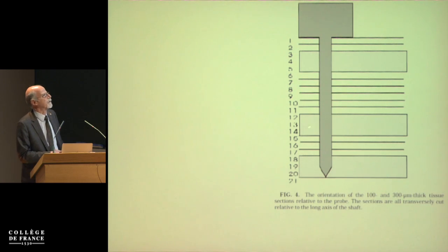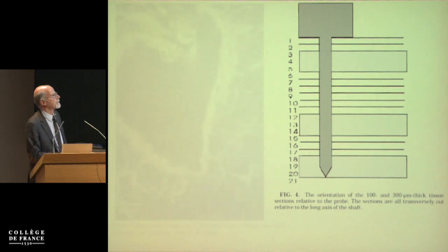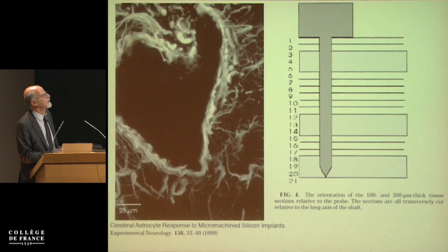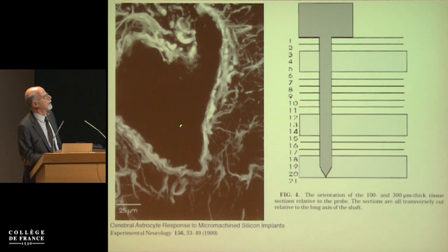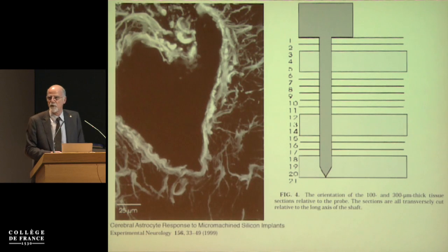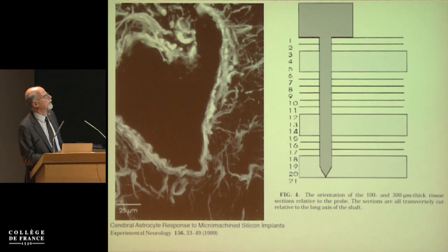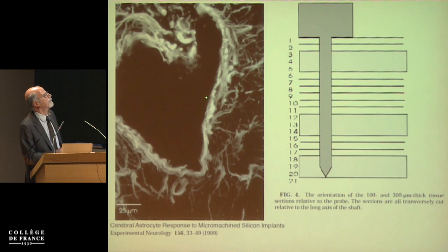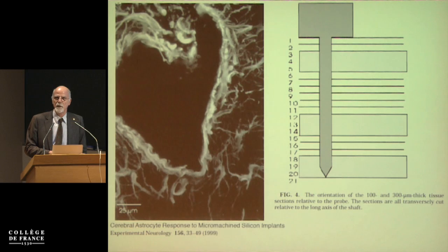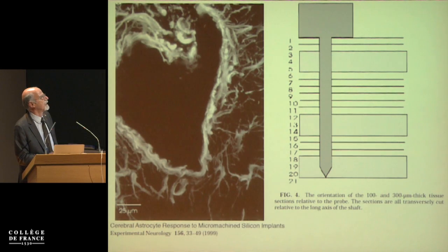What is also important is that usually the electrodes you see here are a few microns, hundreds of microns. So it's a very small electrode, but even though it is small, the scar which is created inside the brain of the implanted animal is very thick. So there is a lot of scar surrounding the electrode when it is implanted, because it's a foreign body, and so it is rejected by the nervous system, and so in practice the scar is insulating and can adversely affect the use of the electrodes.